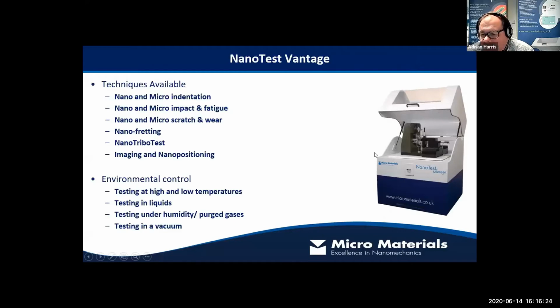Well, we can do it with a multifunctional instrument such as this NanoTest Vantage. So the Vantage is a multifunctional tool we've used in this study. It can perform nano and microscale indentation for measurement of hardness and elastic modulus, which, as we've already acknowledged, is an essential tool in development of hard wear-resistant coatings. And we have nano and micro scratch and wear, and we've already identified that scratch testing is important. And really, for these types of coatings, micro scratch is what we want.